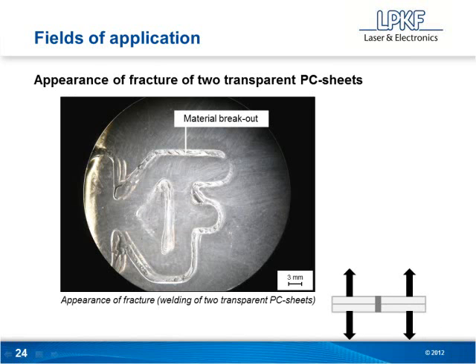This is showing actually an instance where we did a pull test, on that high transparency PC. So you see the material breakout in the weld seam. This is good news. That means we created a bond in the polycarbonate where it's not just a surface tacking. The two pieces of plastic actually fuse together, and as we pulled them apart, you see all the cracking and the micro fractures, and that lets us know that we've actually fused the two parts together.